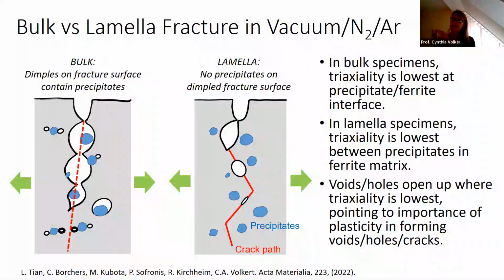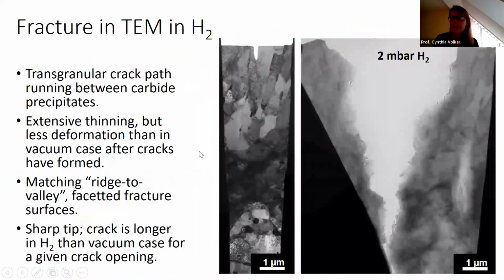So in our opinion, we can bring the TEM results and the bulk results under one picture, and argue that what we're seeing in the TEM is revealing mechanisms that may also be controlling in the bulk case. There are some important differences due to the differences in the stress state, and they result in differences in the fracture surface. Okay, so let me now go on to the hydrogen case, which is, I think, what's of interest here.